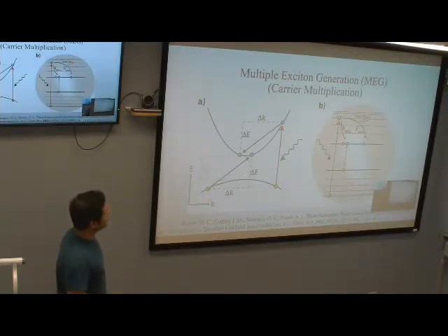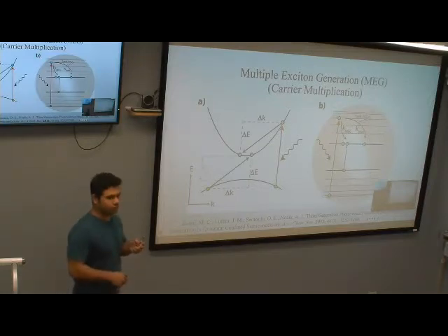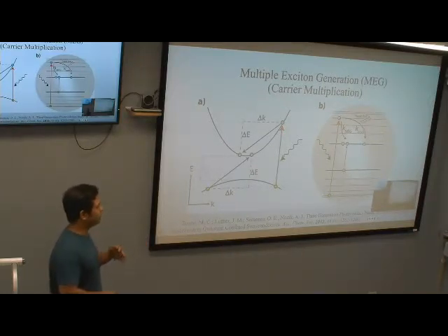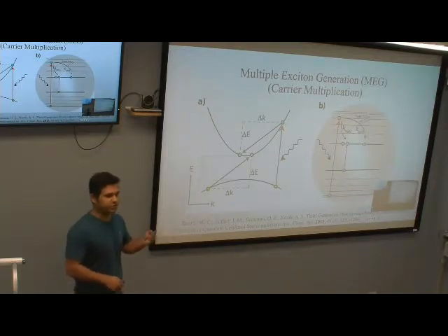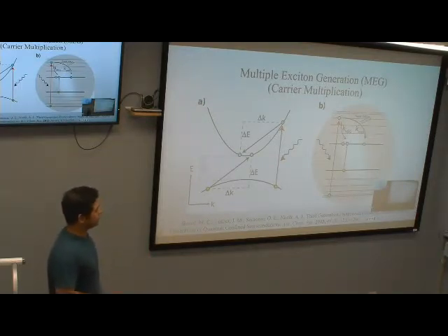So in those types of material, just by absorbing one photon, an electron is excited to a higher energy and creates a hot electron. And instead of thermalization, this electron, by impact ionization, can release the energy, and another ground state electron can absorb the energy and go to the excited state. So the main point is, by absorbing one photon, now you get two electron-hole pairs. Because of that, the overall efficiency of the photovoltaic cell can exceed 100% efficiency. So this is the bulk material scenario.